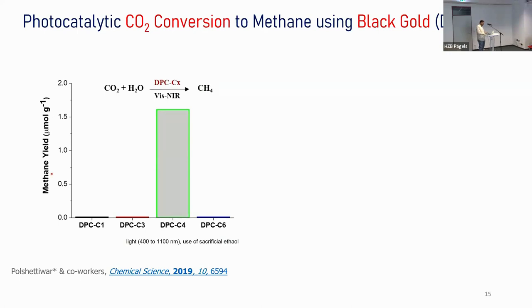However, if you look at this again, look at the y-axis, the unit is micromole per gram. So 1.5 micromole per gram is really a poor number. Even if it is better than what is reported in the literature, it's a poor number. Then the question we ask is, why is the yield low when we have a material which can harvest the entire broadband light? Why is the activity low?